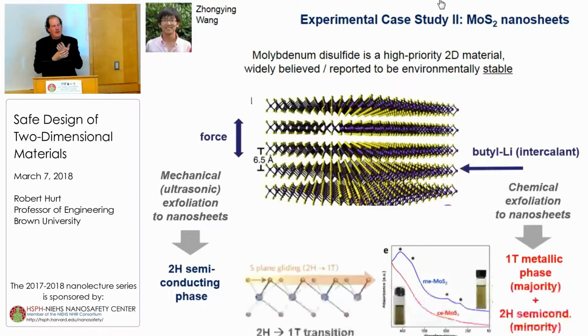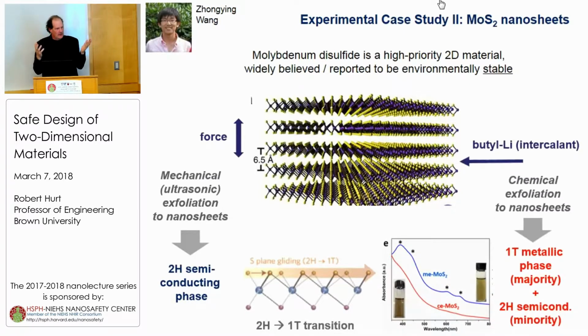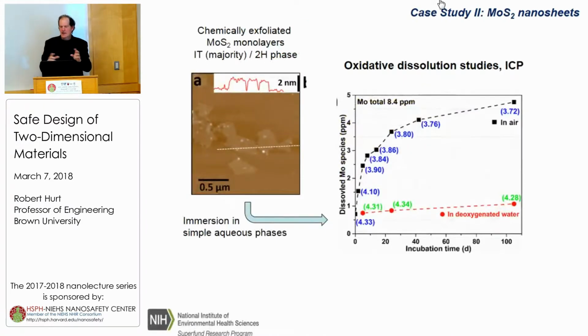A little wrinkle with this material is that if you mechanically exfoliate it, you get semiconducting nanosheets, whereas if you chemically exfoliate it, you get a mixture of metallic and semiconducting nanosheets. And you can tell the difference. The composition is the same, but the sulfur plane glides and changes the crystal orientation. One's metallic and one's semiconducting.